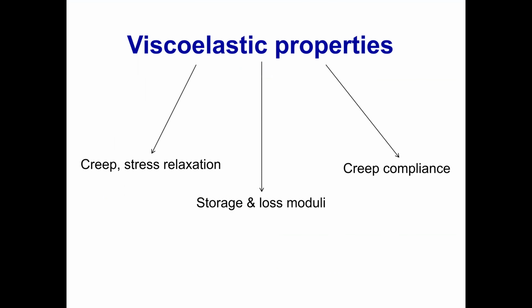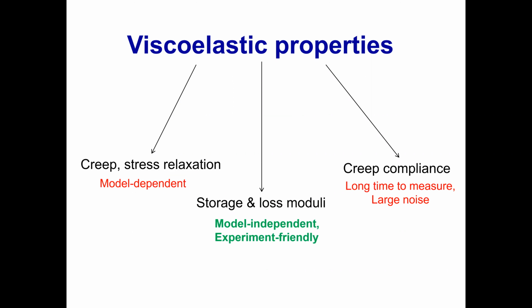So now FT-nanoDMA, different universe, viscoelastic properties of materials. How can you measure it? You can do either creep or stress relaxation. That's what's typically implemented in nowadays force microscopy. In this case, what you do, you simply develop some contact and then simply see how this contact relaxes in time. Or you can measure so-called loss and storage modulus, or you can go to much rarely used measurement of creep compliance or stress compliance functions.